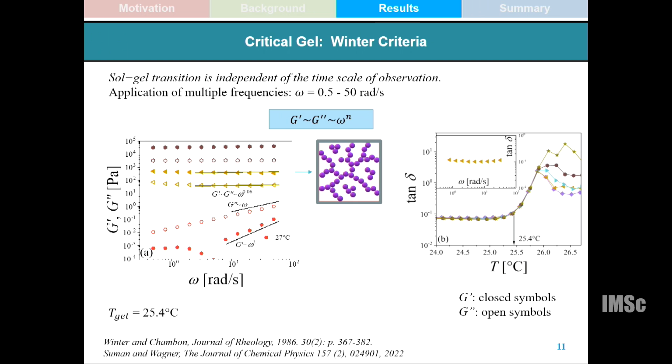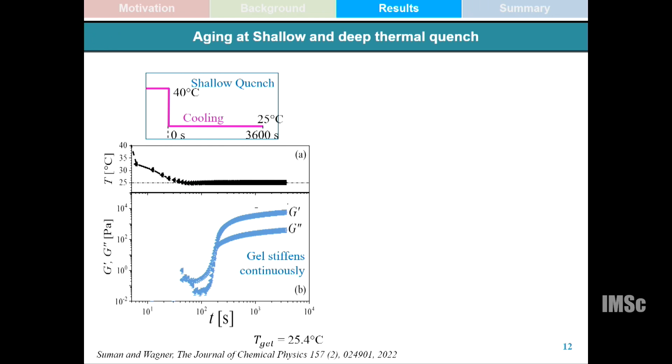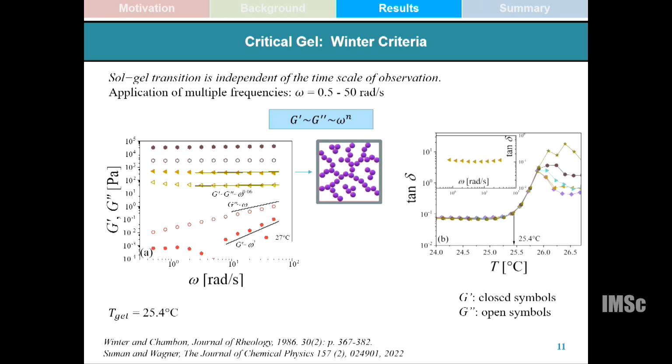which means that if we have a system of these adhesive hard spheres and we make a box around it, we will be able to cross from one part of the box to the other by just following the path of connected adhesive hard sphere particles. So this is the temperature at which there is the weakest spanning percolated network, and we now have a well-defined gel temperature, which is 25.4. The idea of this temperature is only to characterize the gel point. It just has to be interconnected so that it can span the entire space.